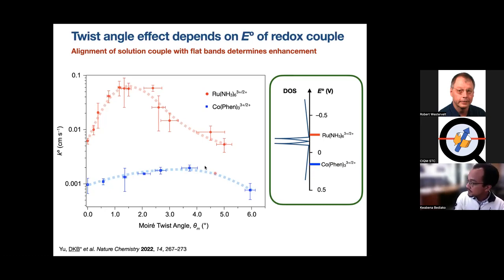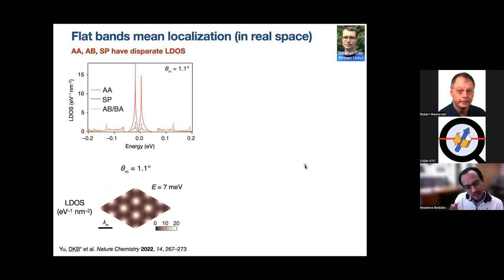And in fact, you can explain why the enhancement is at a larger angle from the fact that at larger angles, you would expect that the van Hove singularities of your twisted bilayer graphene would still be smaller than what you get at 1.1 degrees, but they would be better overlapped with the cobalt phenanthroline. Okay, so let's think about this a little bit more.